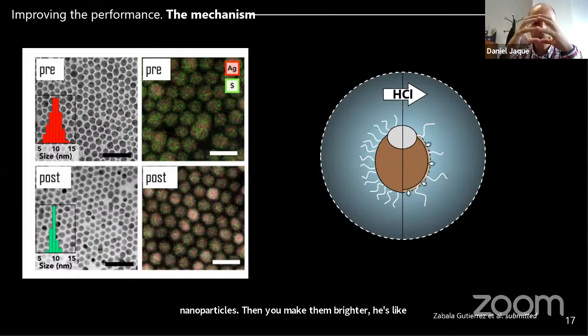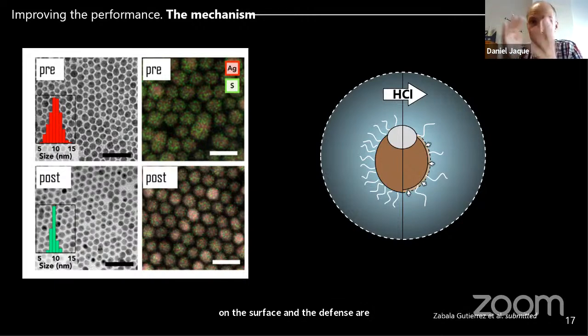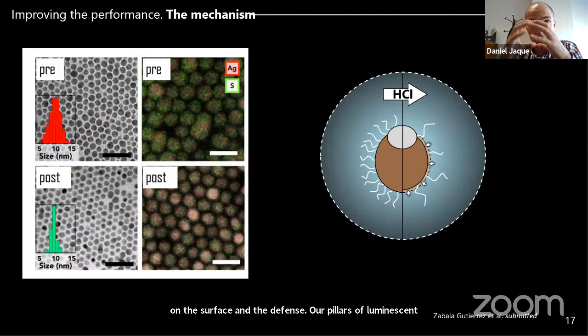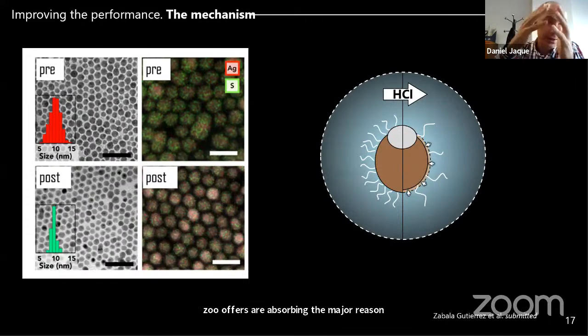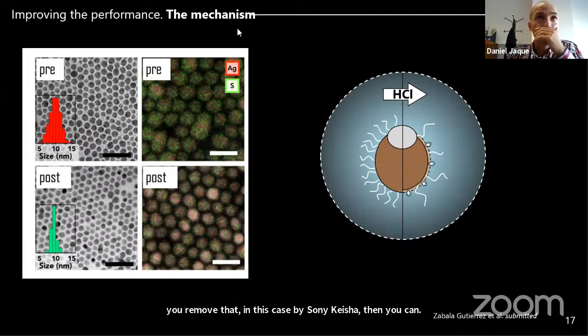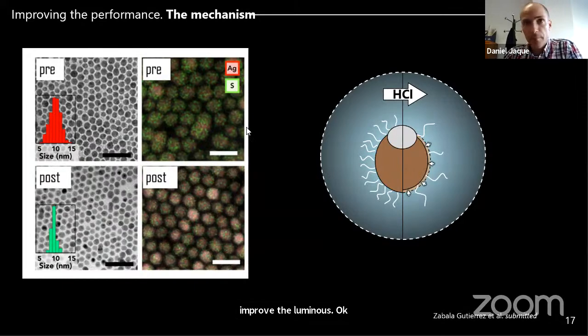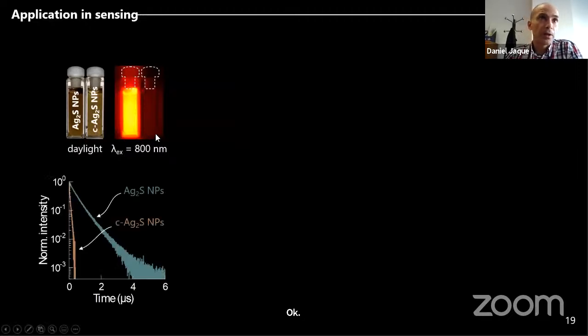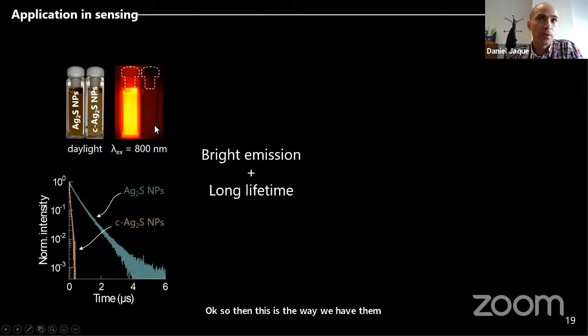So you have the nanoparticle, and you have a lot of defects on the surface, and the defects are killers of luminescence. So when you have a nanoparticle with a lot of defects on the surface, the nanoparticle is not emitting well, because those defects at the surface are absorbing the emitted radiation. If you remove that, in this case by sonication, then you can improve the luminescence, okay? So then this is what we have, that they are much brighter than the normal ones.